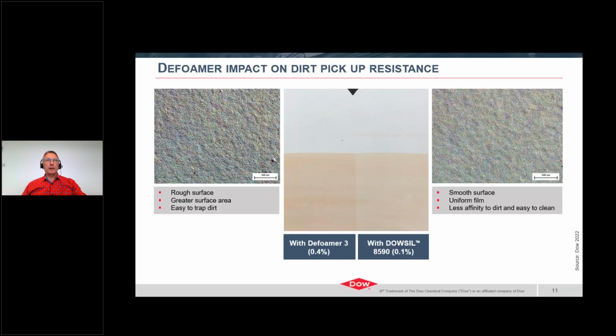And when the actual surface of the dried film is observed by microscopy, you can see on the right of the screen that the surface of the film containing the featured additive is significantly smoother than the one based on mineral oil, probably indicating both the improved performance and compatibility of the material in the formulation.